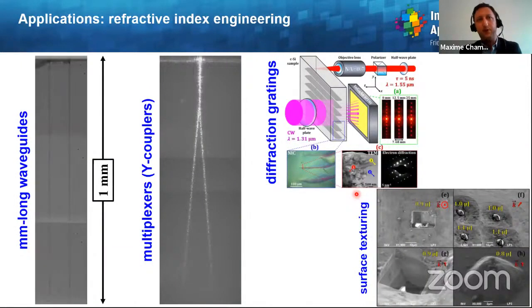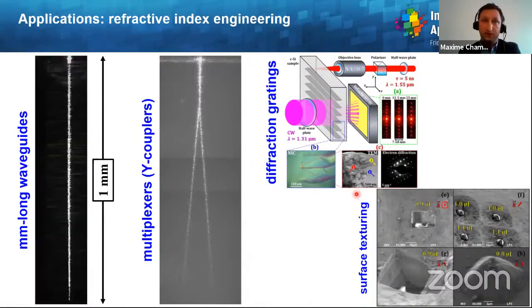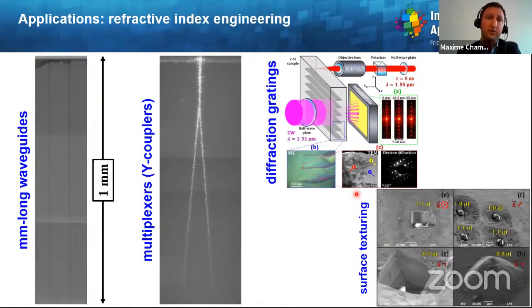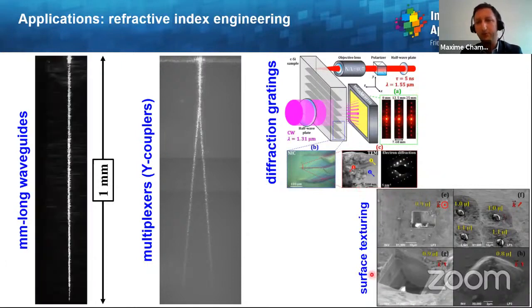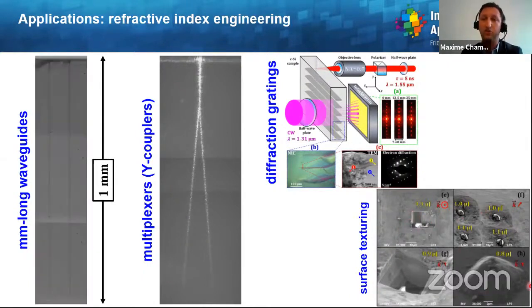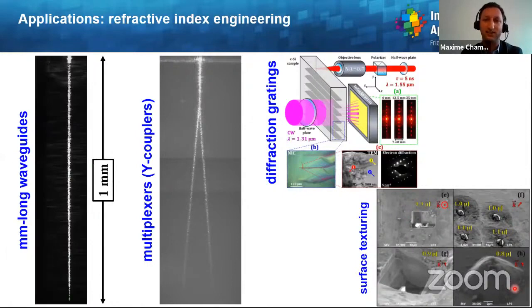Then with this positive refractive index change, it is possible to find some applications in the field of refractive index engineering for writing millimeter-long waveguides. As you can see here on the left, multiplexers for splitting and coupling the light, also called Y-couplers. We have inscribed diffraction gratings, and also we have performed surface texturings, either with negative index change or the positive index change corresponding to the waveguides, where we see some micro pyramids on the surface of silicon after selective chemical etching.